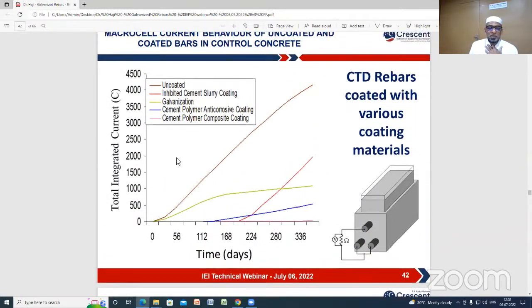These are the values or behavior in this test at the end of 1 year. Here we can see that the galvanized rebar's corrosion rate is very low compared to the uncoated rebar. In the uncoated rebar, there is a large amount of current development, which indirectly shows that heavy corrosion activity is going on. In the galvanized rebars, we find minimal corrosion activity. This corrosion activity is also zinc corrosion activity, not steel corrosion activity.